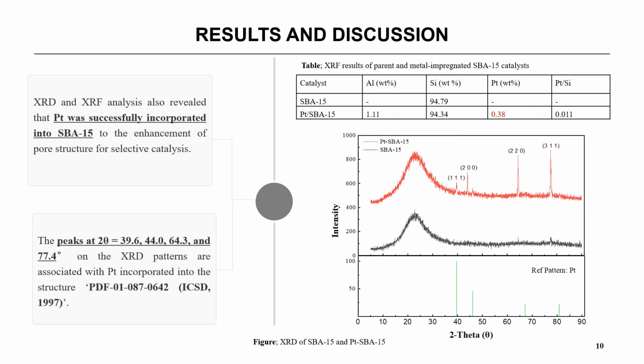In addition, the elemental compositions from XRF as well as XRD peaks at 2 theta, 39.6 degrees, 44 degrees, 64.3 degrees, and 77.4 degrees confirm the successful incorporation of platinum onto SBA-15. Peaks analysis using X'Pert HighScore software and ICSD database correspond to reference patterns of platinum as seen on the XRD diagram.